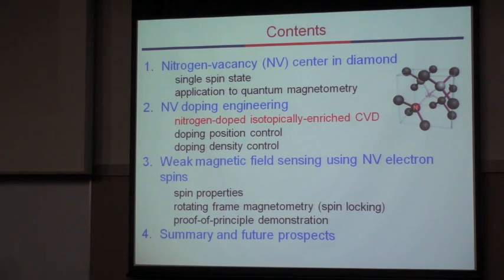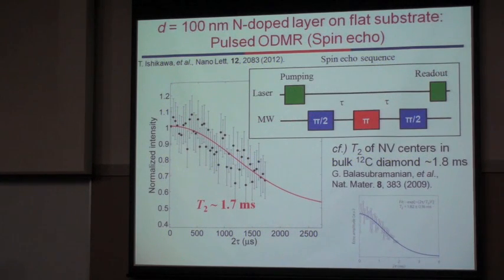So first, I will show you the result of measurement of spin property of our sample. This figure shows the result of spin echo measurement in 100 nanometer sample. We can observe the very long coherence time of spin triplet state, which is of the order of millisecond.